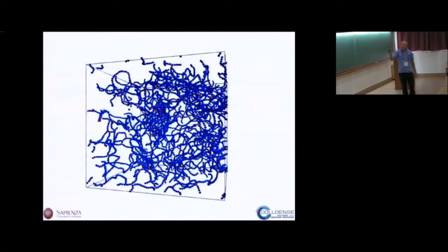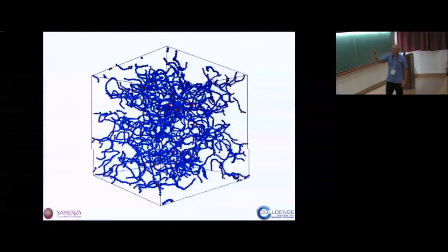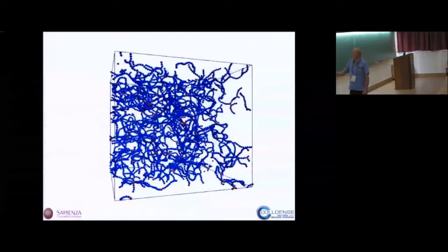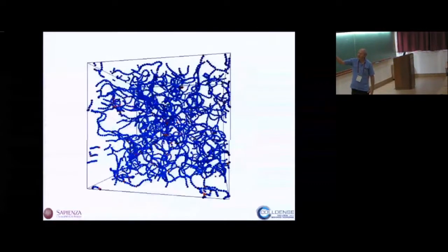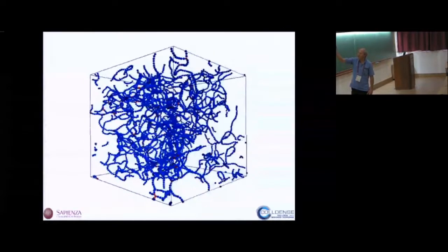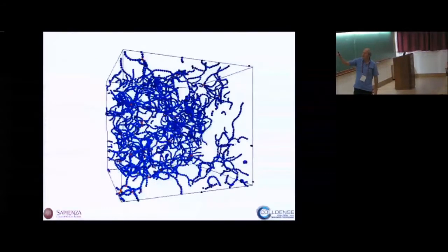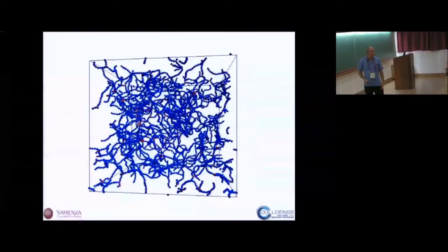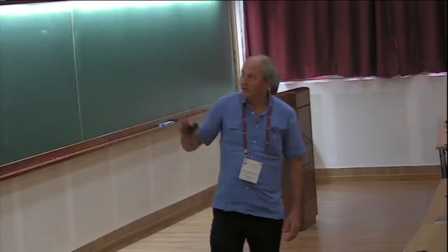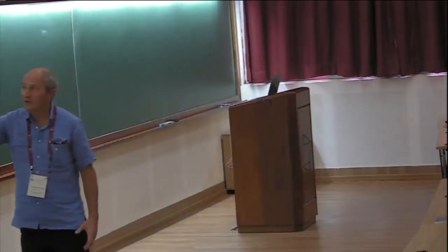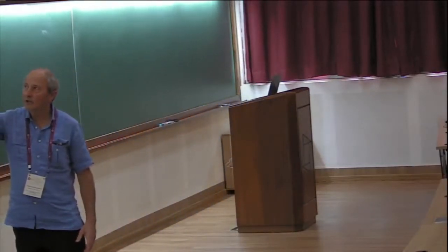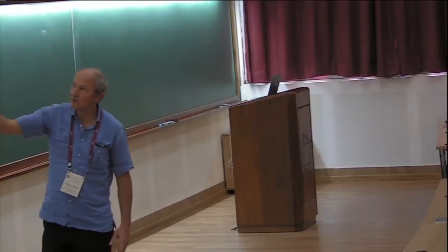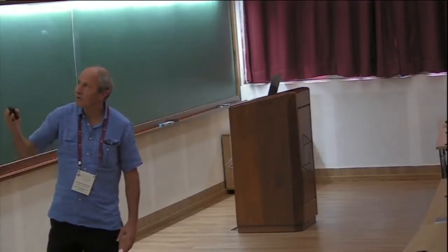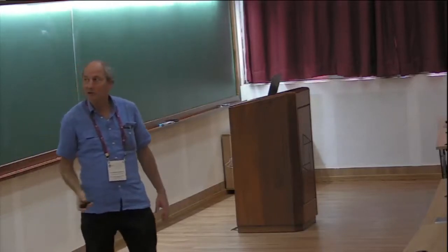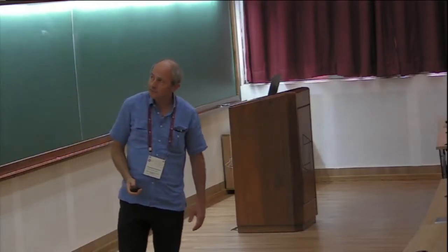And this is how the system looks, for example, if you want to think of what this liquid is that coexists with the gas at very low density. It's really a gel, what you have in mind as a gel. It's a chain of bifunctional particles connected with branching points, which are three-functional units. So you can really provide a very nice description in terms of statistical properties of the network. You can count everything theoretically: the length of these chains, all the branching points, the size of this cluster, everything. We have a complete understanding of these materials.